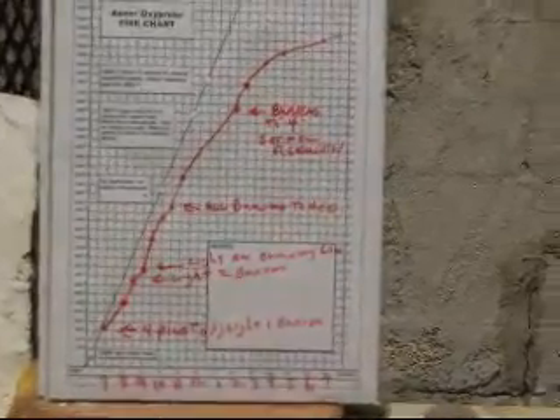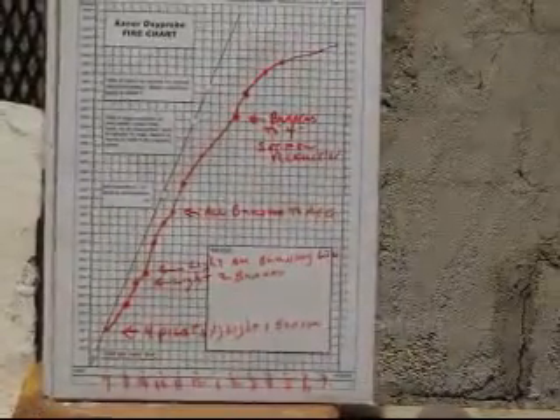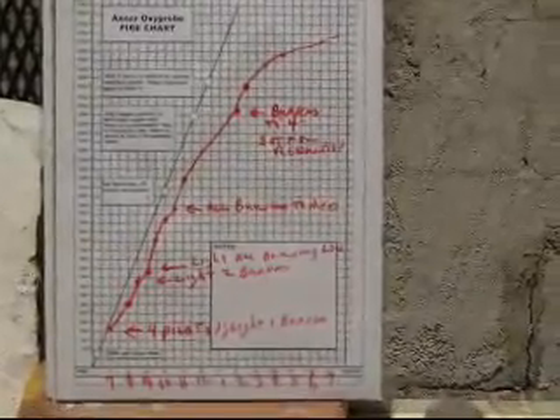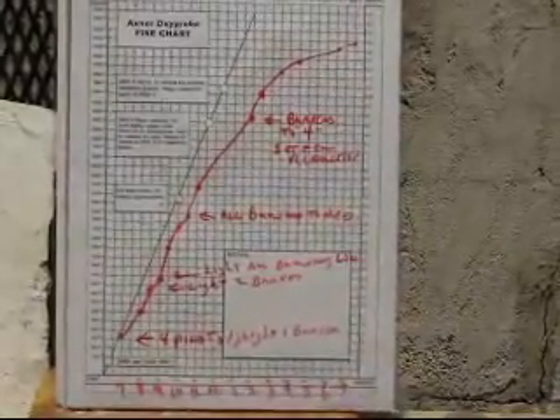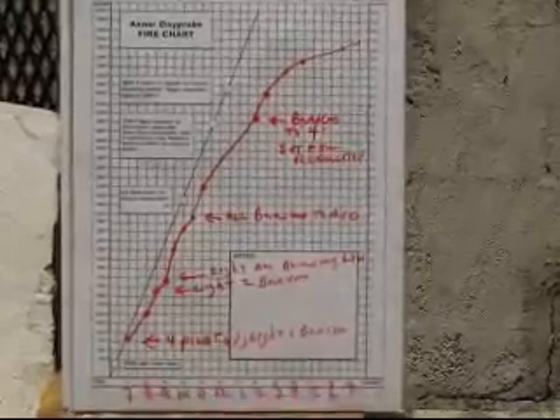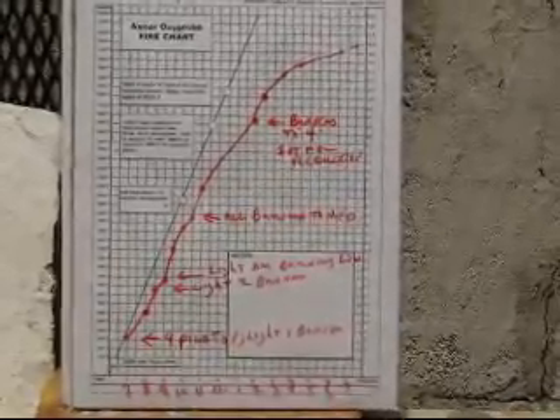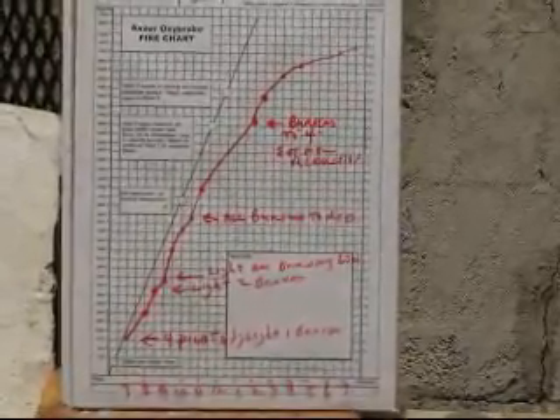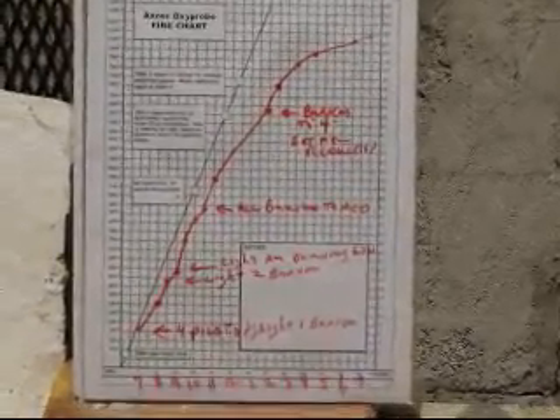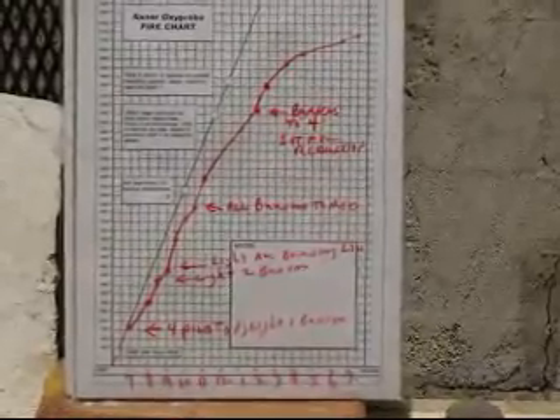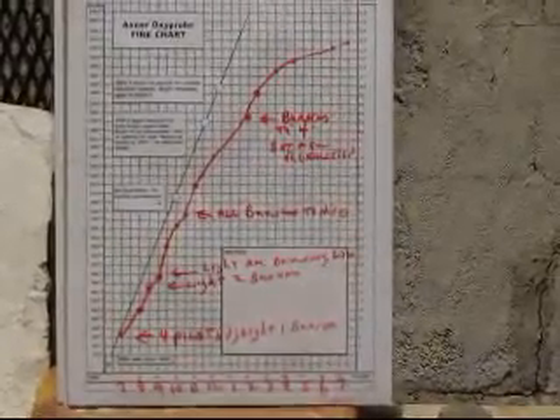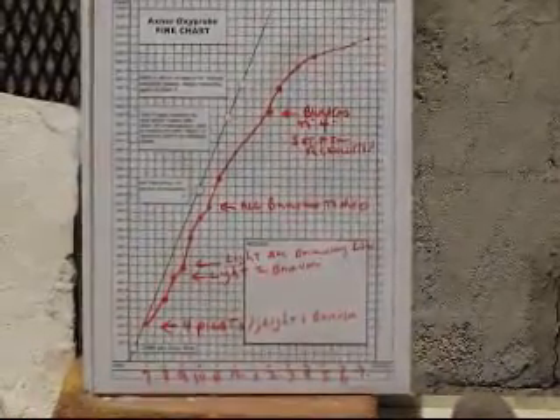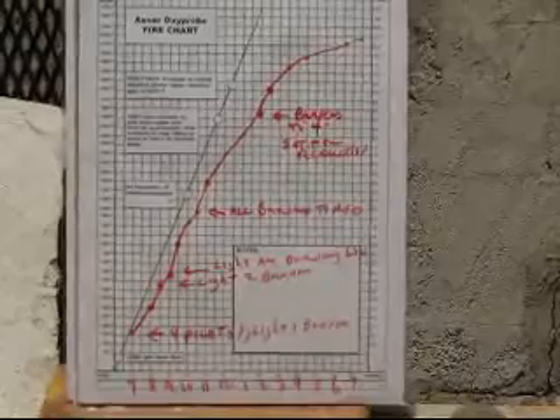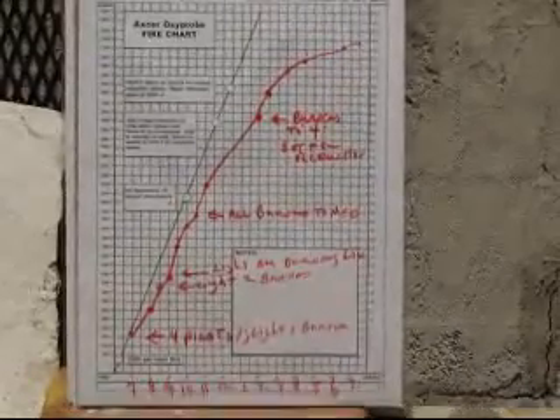I can open the damper a little bit to try to improve the heat flow through the kiln, because I may be in too much reduction, or I can increase the gas to try to make it heat faster, but my gas is already high enough, and so I'm going to just let it sit because I just checked, and cone 10 is starting to bend on the lower part of the kiln. So I think we're actually doing okay.